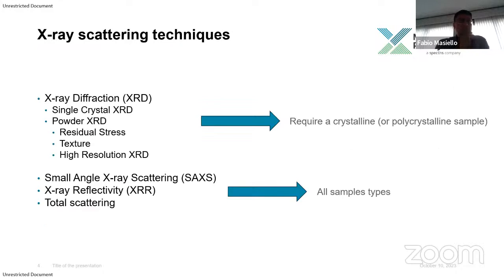So, start with the X-ray scattering techniques. I mentioned before X-ray diffraction, where we can separate between single crystal X-ray diffraction and powder X-ray diffraction. And then I would say the methods based on powder X-ray diffraction are just giving you some different information. I will cover quickly residual stress, texture, and high resolution XRD. All of these techniques need a crystalline sample or a polycrystalline sample in the case of powder diffraction. They will not work with, for example, amorphous samples or liquids or anything.